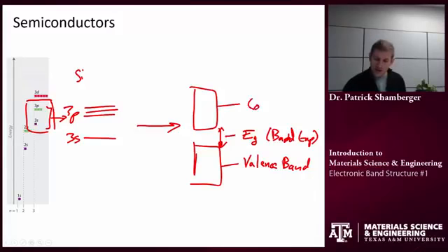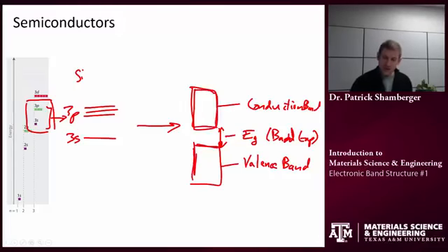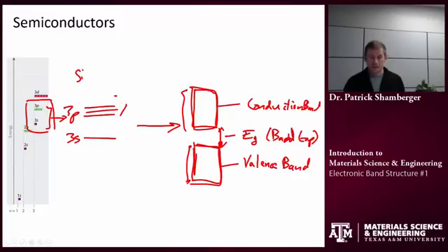And I would call this the conduction band. And we get this separation between these 2 bands because I'm combining 2 different kinds of orbitals, and they're interacting and they're mixing, and they lead to 2 continuums, 2 bands, and a gap in between.